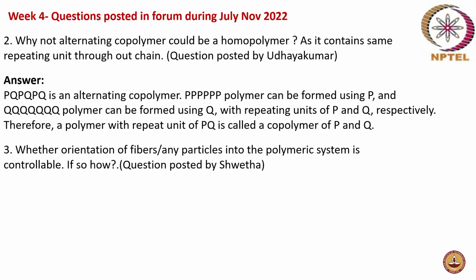You can also think of condensation polymers like polyethylene terephthalate, where ethylene glycol and terephthalic acid react. Ethylene glycol can form a polymer by itself, which is polyethylene oxide or PEG, polyethylene glycol, whereas terephthalic acid, I don't think you can form a polymer of its own. Correct. So when considering this alternating copolymer, if PQ is able to form a polymer separately, then it is possible, but it becomes a normal homopolymer. But if it doesn't form a polymer separately, then it's not possible. It's a good question.